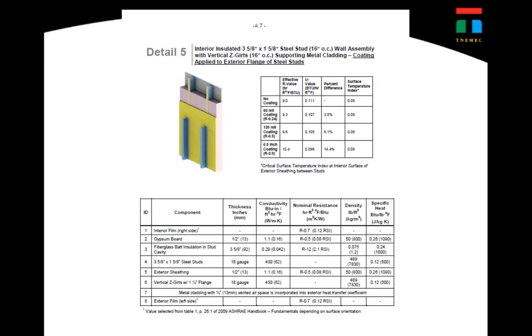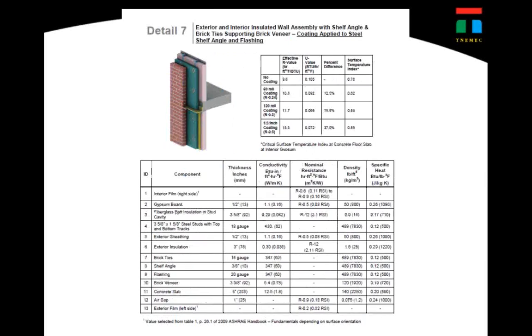And I looked at the numbers and I'm like, wow, at 60 mils, we're even better in terms of thermal bridging than we were on the previous one. One I thought was most interesting, which was significant, which everybody has a problem with, is this one here, with brick shelf angles. I mean, everybody has this on virtually every building you do, just about. And look at the numbers here. At 60 mils, we're seeing a 12.5% savings in terms of actual energy loss.